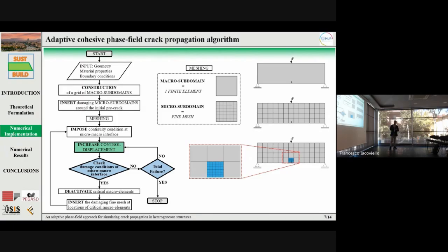So the interface where the crack damage variable is greater than a set threshold is marked as a critical micro-macro interface, and the adjacent macro subdomain is marked as a critical macro element. Once a critical macro element is detected, the damage fine mesh is inserted in this region.